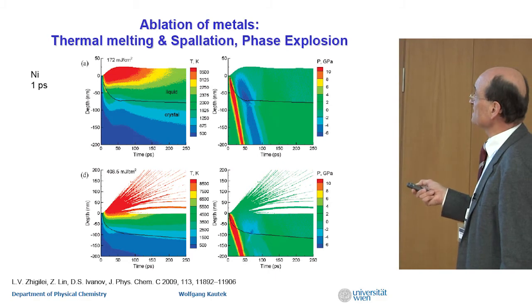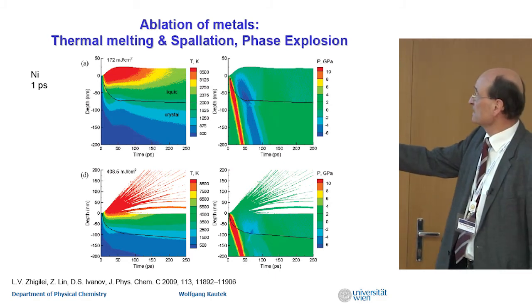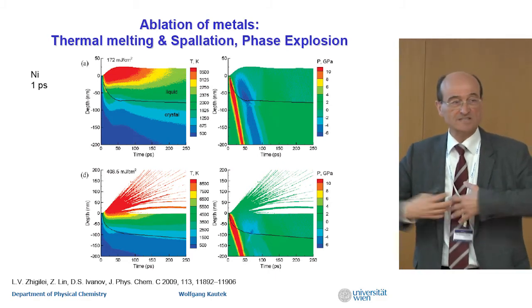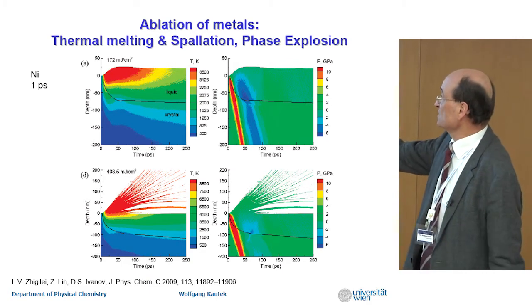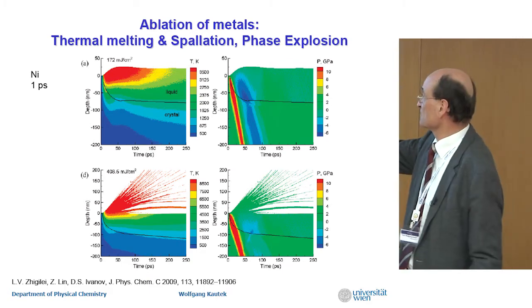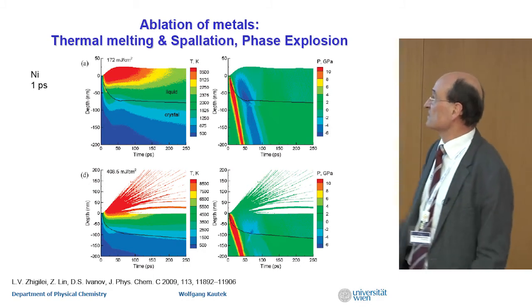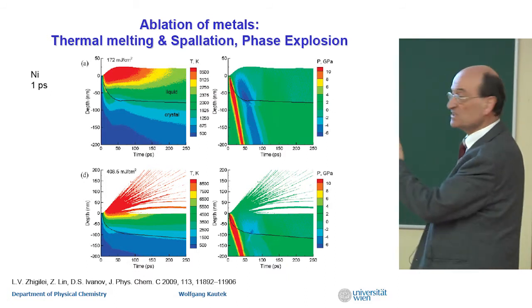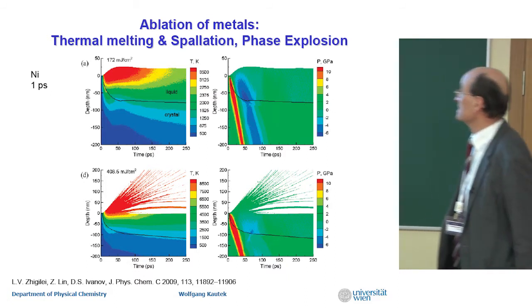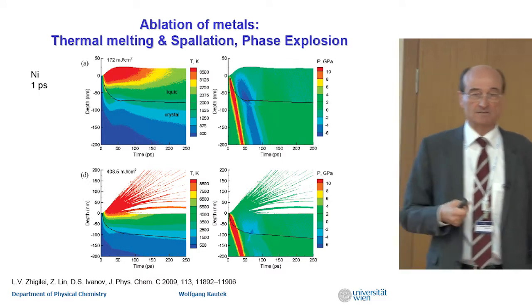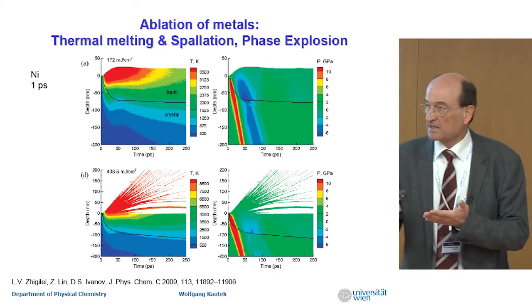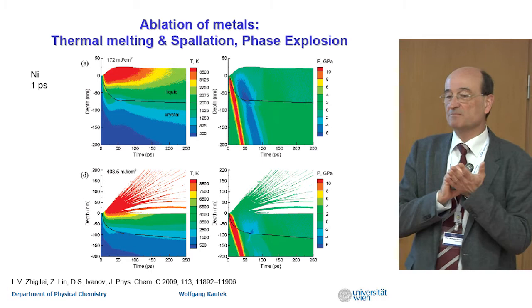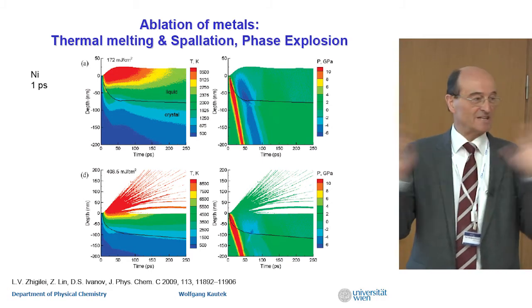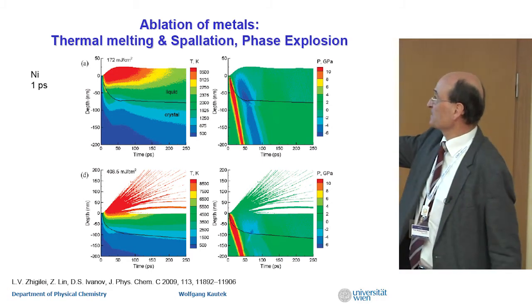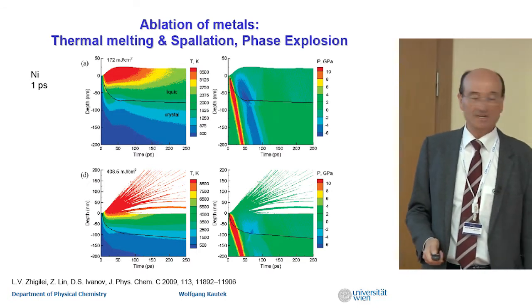If you increase the temperature, the energy of the laser, then of course you are disintegrating the material, and you see that hot splashes are coming out of the material at a certain pressure. So that's how people discuss these things in recent years. You see, that's quite recent. Now, that was the metal. And metal micro machining is difficult because the metal makes splashes. As you see, these splashes are a problem in machining.